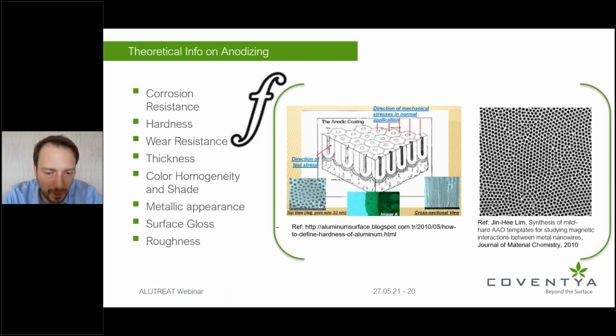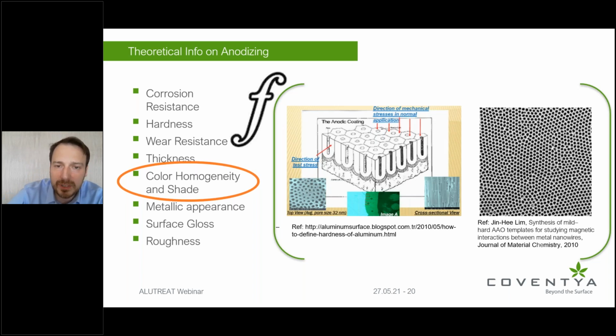So the complexity and the need to control these parameters is paramount, because it's a conversion, and the way we convert the aluminum, which is present on the surface, to the aluminum oxide determines all the attributes that we talked about, like corrosion resistance, hardness, wear resistance for us today, which will be very important, color homogeneity and shade, and also metallic appearance. Quite frankly, all of these attributes are a function of how this pore structure and these individual pores are distributed throughout the surface, because we are using them as a template, for instance, in our case for coloring, in order to precipitate the metal salts. So the more orderly they are distributed, the better the color homogeneity is going to be.